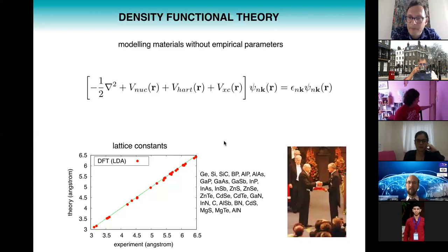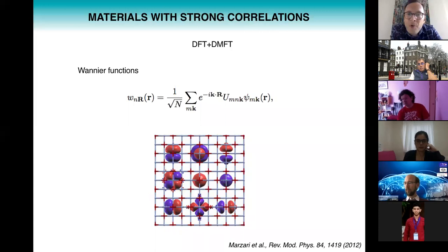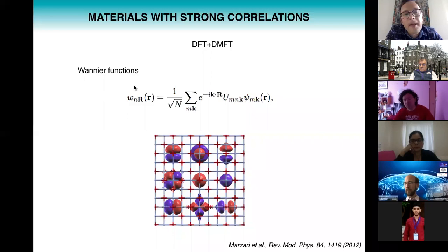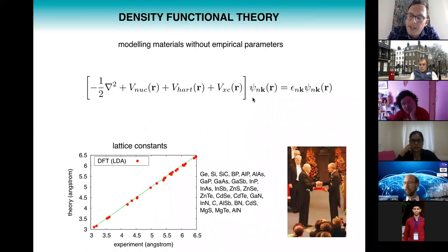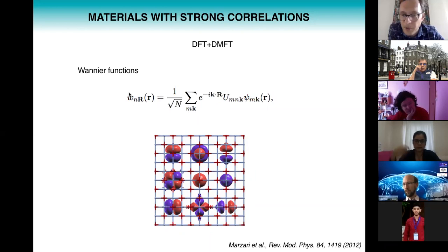DFT lattice constants calculated for 20 different materials lie basically perfectly on the diagonal when plotted against experiment, achieved without tuning any parameters — a great success of theoretical materials science. Walter Kohn, who invented the theory, was deservedly awarded the Nobel Prize in Chemistry. The connection between the first-principles world and the model Hamiltonian world is through Wannier functions: while the Kohn-Sham solutions are Bloch waves, going to localized quantities via Fourier transform gives us Wannier orbitals, which serve as a basis for the Hubbard Hamiltonian.